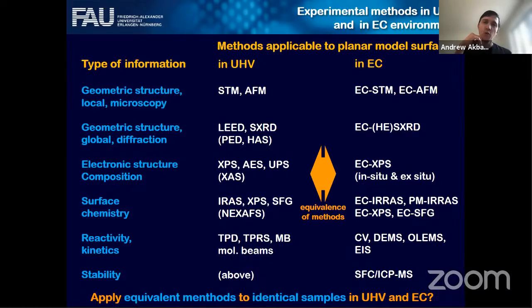Right. But on the way back, I'm curious what actually happens, because my understanding was that you have to dry the sample actually. In vacuum. Yes. Whenever you dry, even any ppb levels of contamination will... perfect question. The way back is an even greater challenge. The one way is tricky, but the way back is certainly very, very tricky, because on the way back, there's no way of not breaking the potential control without having electrolytes. At the point where you take it out, you break the potential control and the electrolyte is still there. And then you only can hope for the best. That depends very much.